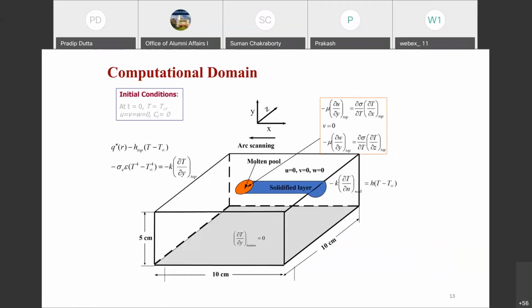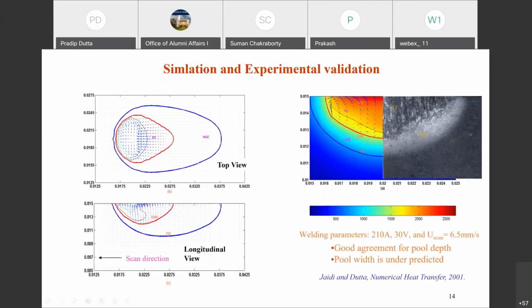So keeping that in mind, putting all these factors into the models, we do the modeling. This is our computational domain with boundary conditions. I will not go into the details of each, but there are conditions on the surface, there are conditions on the sides, and the bottom is insulated and so on. Then, with just one slide, I would like to show a representative result, which gives the weld pool shape and size along with the velocity vectors. It's a transient process. We can catch the process right from the beginning of melting all the way to the full-blown weld pool, and then the solidification process as well. Finally, when we study the microstructure and find the heat affected zone and the weldment zone, there is a good match. Again, it's not a numerical match that we are trying to provide, but at least the trend we can capture as a result of it.